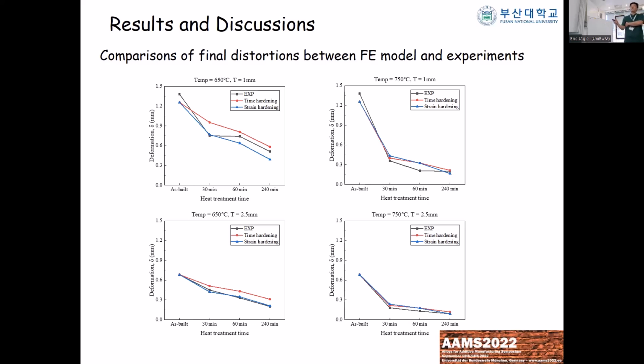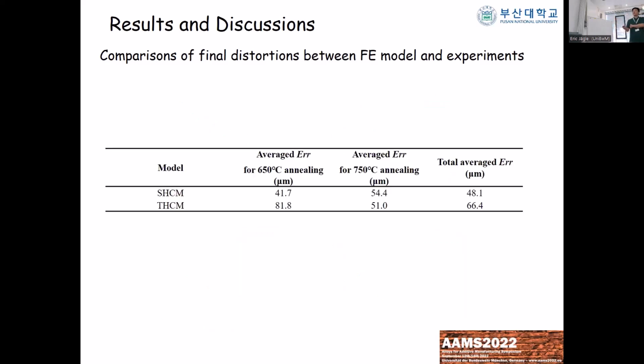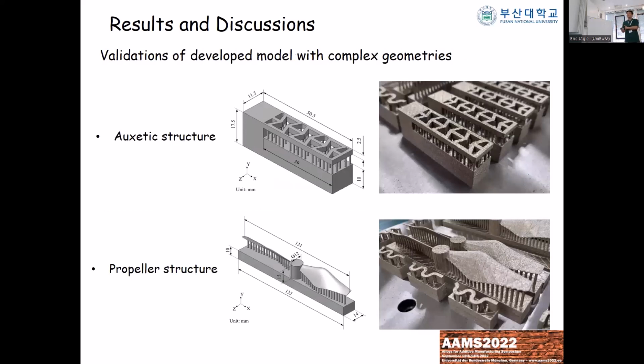And another thing is that for this particular material, 316L stainless steel, the strain hardening model is slightly better than the time hardening model. Maybe that depends on the material, I think. And when we calculated the error and compared it to all deformation, the error bar was something like 5%. And then we checked the validity of our developed predictive model. So we wanted to figure out whether our model can really be used to predict the deformation of annealed structures with complex three-dimensional shapes. We have designed two different special structures. One has an auxetic shape with supporting structure, and one is a propeller with supporting structure.